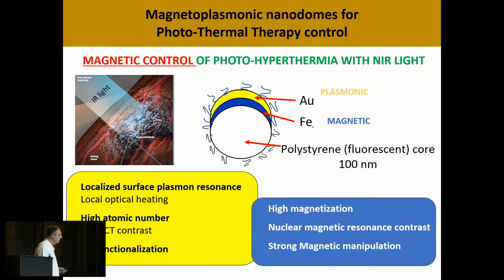We designed this new type of nanoparticles that we call nanodomes. And what they are is a polystyrene bead, which is a commercial bead of about 100 nanometers. And then we cover them just by a dome with iron and gold on top. Why did we choose these two materials? Well, gold has a localized surface plasmon resonance, which I will show you that we can use for local heating.